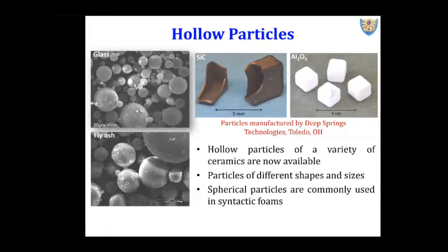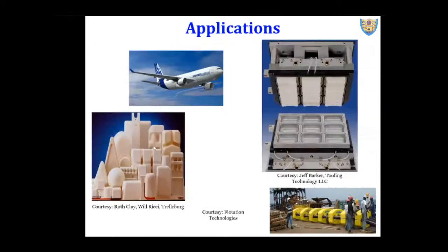In aviation, as thermoforming plugs, you can see a thermoforming plug here. Especially, these are used in thermoforming plugs because they have a minimum coefficient of thermal expansion because of the hollowness. Then these are also used in seashore applications, wherein crude oil is taken from somewhere deep in the sea to the shore, and a pipe has to be laid. If you just lay the pipe in the water, because the density of the entire pipe with the fluid is more, it sinks, ruptures, and there is oil leakage.